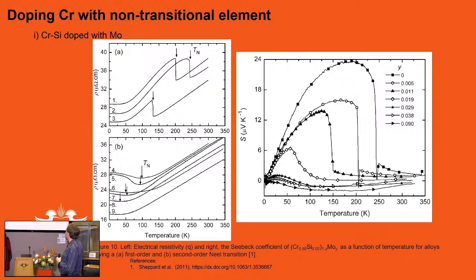I started working on chrome silicon. I'll come back to what the molybdenum is doing here now. But silicon, together with iron, is the only two elements that actually produce these very sharp transitions. We call them first order. In some measurements, they're actually discontinuous, depending on the quality of your material. But we were tracking what happens if we start following this first order transition. We add molybdenum. Now, why moly? Silicon has the problem, if you add too much, the quantum critical point, this low here, starts being problematic. So you can't track certain transitions.